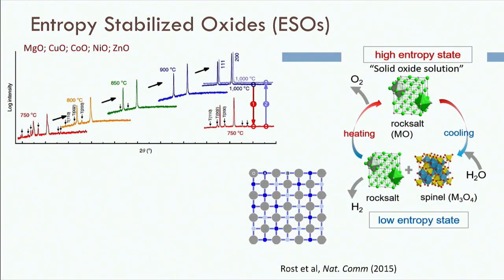And we were looking for materials that would undergo phase transition, because in a phase transition you can get large entropy change. We ran into this material that was basically discovered 2 years ago called entropy stabilized oxides. What you do is you take a bunch of oxides, magnesium oxide, cobalt, copper, etc., and you mix them together and heat it. It is known that when you heat these oxides, you form essentially a stable structure. In this case, it's stabilized by the entropy of mixing of the cations in a matrix of oxygen.